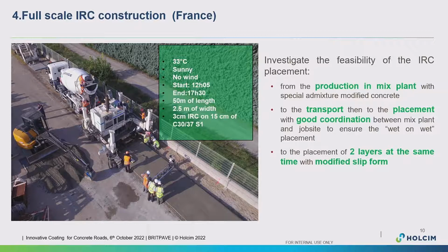And then we move to the full-scale construction investigation. So we launched it in 2017 in the south of France to test the possibility of production and then the placement of this solution. And here we did a small innovation by using a classical slip form, bringing an asphalt vibrating screed. The idea here was to test the placement of 2 layers at the same time.